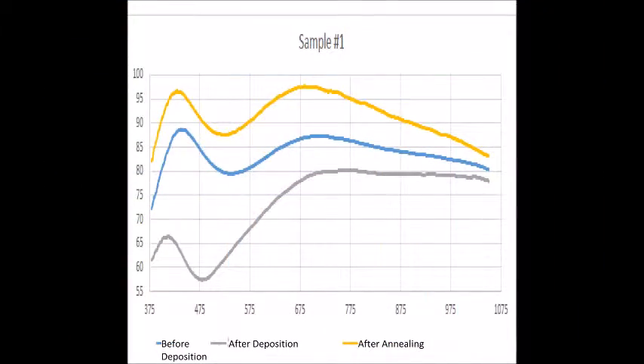After measurement, a transmittance and reflectance curve will be obtained. Here you can see the transmittance curve, and here is the reflectance curve. Here is a summary of the transmittance data through the metal nanoparticle deposition process. The blue line represents the substrate before deposition, the gray line is the transmittance after deposition, and the yellow line is after annealing. As you can see, metal nanoparticles improve the transmittance data of this substrate.